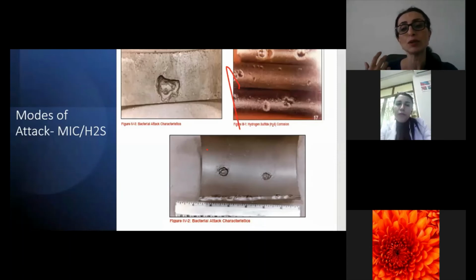SRB bacteria cause severe corrosion, but the biofilm of this bacteria is usually very weak. Usually the APB and GHP biofilm accommodates SRB, and when we see a combination of both of these bacteria existing in a system, we need to flag it, because SRB can be accommodated by APB and GHP biofilm, which is very strong and sticky stuff. The polymeric material helps create a localized corrosion environment and promotes bacteria growth, which could make it more difficult to mitigate the corrosion. Factors that promote the occurrence of MIC include low velocity, deposit accumulation, high water cuts, and increased bacterial levels. This is about MIC, microbiologically influenced corrosion.